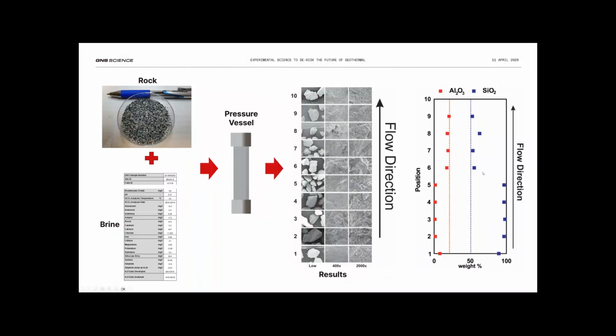And so on the right here you see an example of the SEM EDS results. So the positions are the same as in the SEM photos. And this plots alumina and silica concentration on the surface of the grains. The dashed lines represent the average unreacted rock composition. So the blue is silica, the red is alumina. And what you can see there is very strong silica scaling, and you can see it in the SEM photos by the spherulitic sort of rounded surfaces, and then at position 6 they disappear. And from 6 to 10 there isn't any. And you see that it's reflected in the surface chemistry.